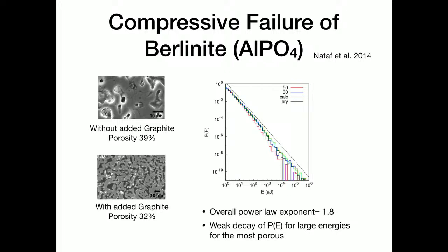So this is compressive failure of a material in which porosity has been controlled by adding graphite and also different ways of manufacturing it. And for these 4 types of samples, which differ in their porosity from 30% to 50%, I think, I forget, what is seen is that the overall power law exponent is roughly 1.8, and there is a weak decay of P of E for large energy for the most porous. So this one is the most porous.